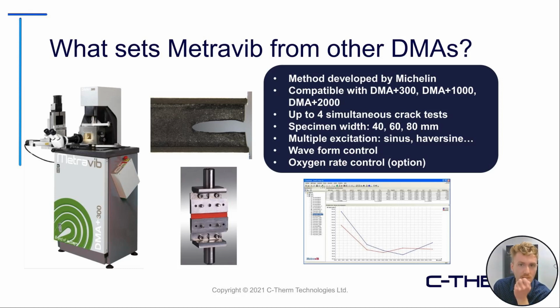What else separates us apart is crack growth. Crack growth is one of the more hot topics that we've had a few webinars about. So if you're interested in crack growth, I'll leave it to some of the recordings to talk about. This method was developed with Michelin in mind. It's able to measure up to 4 simultaneous cracks.